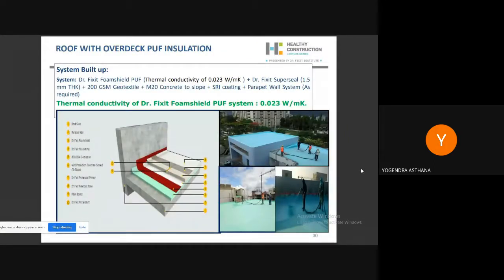And the other version of this material is called Foam Shield, which has higher thermal efficiency and a better K value. It has a K value of 0.023, and to achieve a requirement of R value of 3.5, this PU foam requires a spray foam layer of around 65 mm thick. It will give the insulation value, R value, of 3.5.